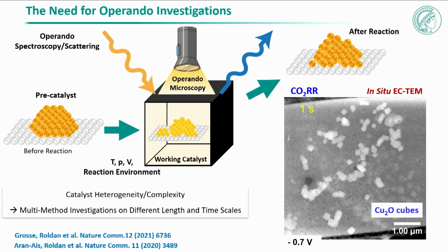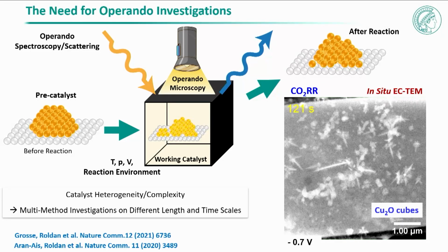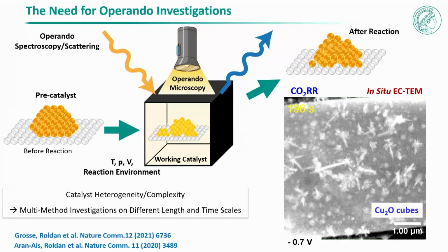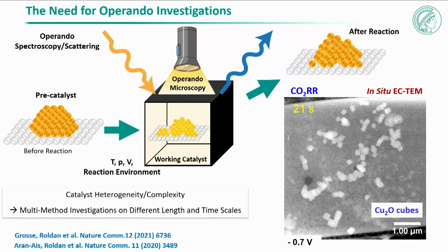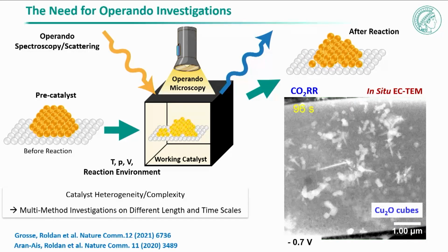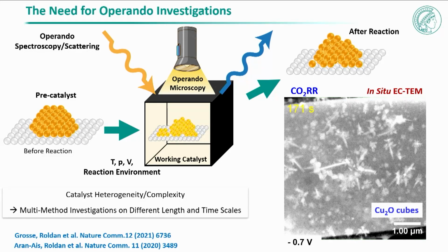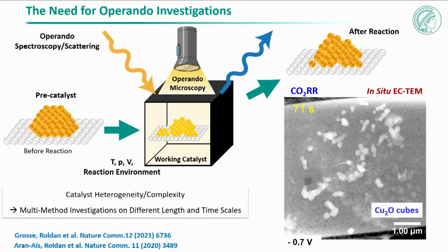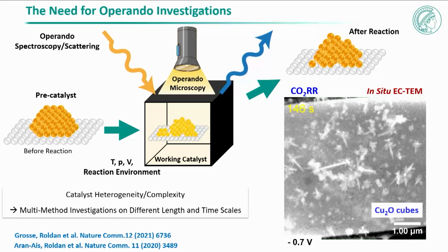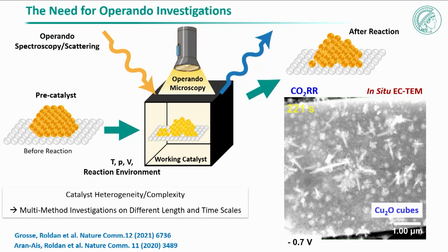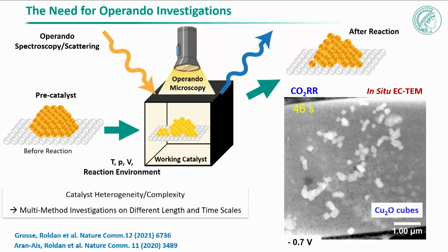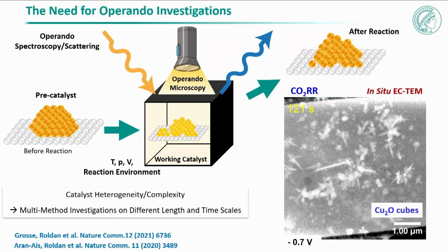So this is just an example of how we make solar fuels. This is the conversion of carbon dioxide into fuels, for example, ethanol. And I just put this as an example, again, about the dynamics of this catalyst. We have CO2, we have an electrolyte that is potassium bicarbonate. I'm looking at all of this imaging in an electrochemical cell in a transmission electron microscope. And you saw that at the beginning, I make these cubic structures. These are copper oxide cubes. But very quickly during the reaction, you see the mobility of this structure, dendrites are forming. So again, high complexity, and this structure and changes in the composition are going to determine the performance, in this case, the activity and the selectivity of these materials.